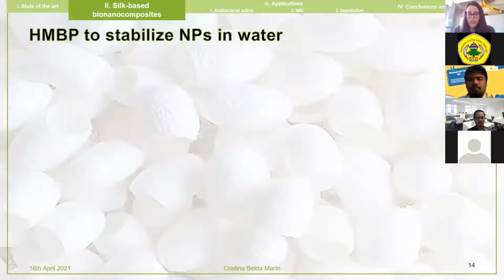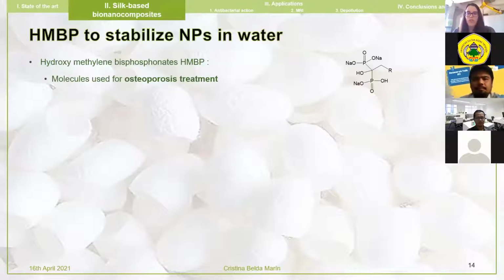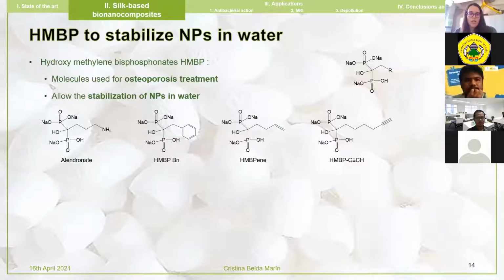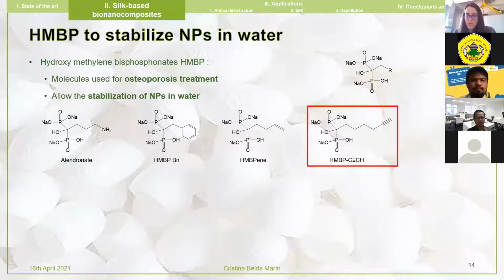So first we have to synthesize nanoparticles. Here we want to have metal nanoparticles that are synthesized in a green manner and not in organic solvents. So the idea is to use hydroxymethylene bisphosphonic acid, which are molecules that are already used in osteoporosis treatment, to stabilize those nanoparticles. The literature has used some of those molecules to stabilize nanoparticles. Here we decided to choose this one because the presence of a triple bond at the end allows an easy functionalization by click chemistry if we want further to add either fluorochromes or bioactive molecules, for example.